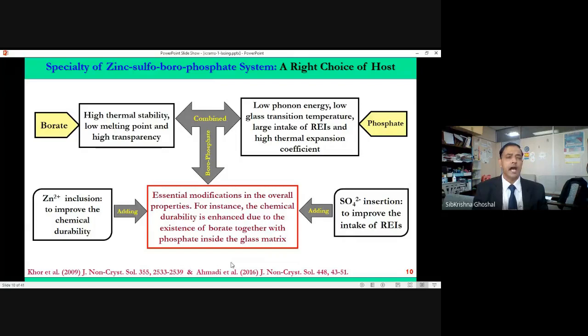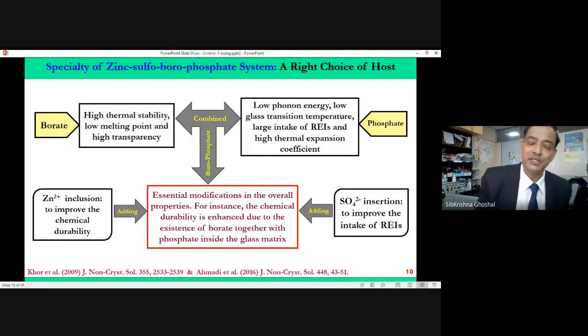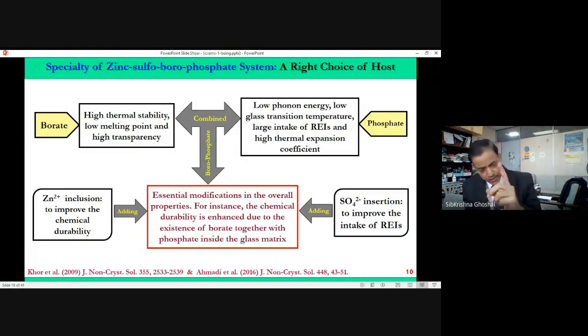Borate has high thermal stability, low melting point, and high transparency. That's why we choose borate. Phosphate we choose because it has low phonon energy, low glass transition temperature, and a large intake of, it can take a lot of rare earth concentrations. Zinc we use to chemically stabilize the network or the glass ceramic structure, and sulfate we use basically to improve the intake of rare earth. So this is already a nice kitchen chemistry. We cook up all this material to get a good functional material. That's why we call this glass functional glass.